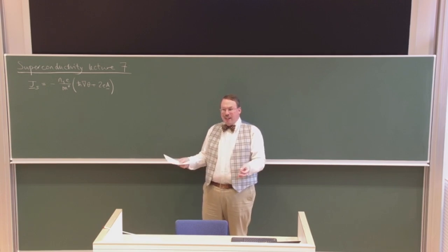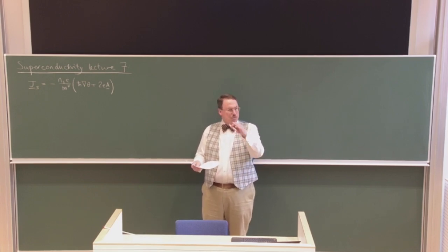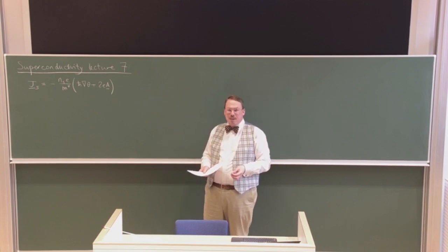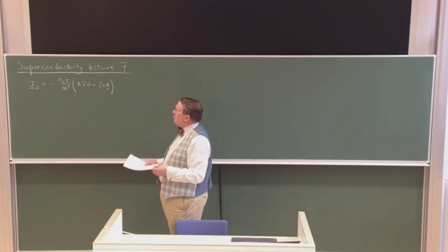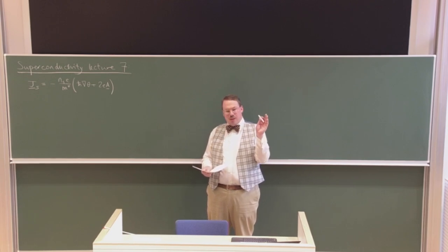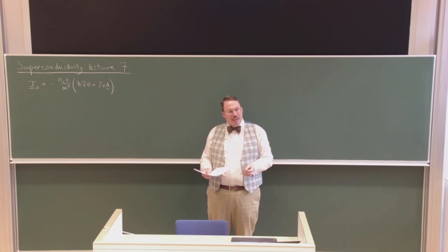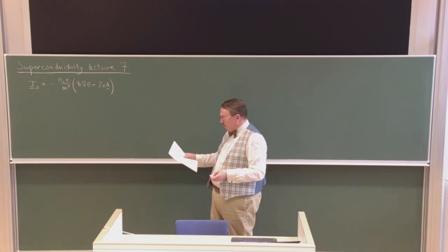And we showed that that leads to the London equation, which gives you exponential decay of the magnetic field as you move in from the surface. So we can show that the resting state of the superconductor is a zero field state, and if you put something on the boundary that's inconsistent with that, it will decay exponentially over a length scale, which is the London penetration depth.